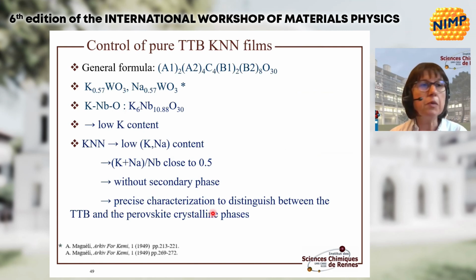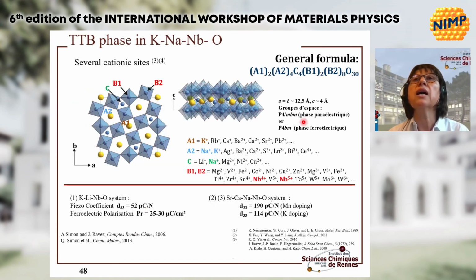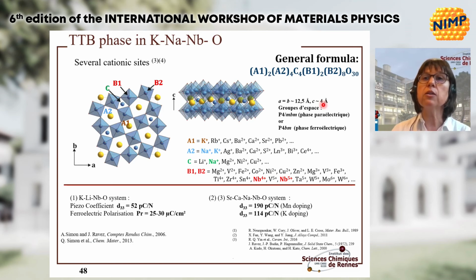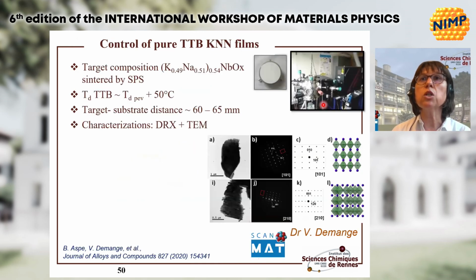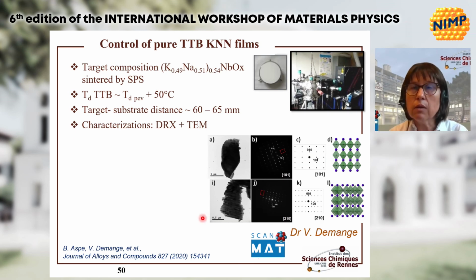Precise characterization has been necessary to distinguish between the TTB and the perovskite crystalline phase. Indeed, you can have a look here at the lattice parameters, and we can see that these A and B parameters are more or less 3 times, and 1 for C, in comparison with the perovskite. That means we have an effect of substructures that makes it difficult to distinguish with X-ray diffraction only. So X-ray diffraction has been combined with transmission electron microscopy performed by Valérie Demange. And in this case, only with very complete characterization, it has been possible to distinguish between the perovskite and the TTB.